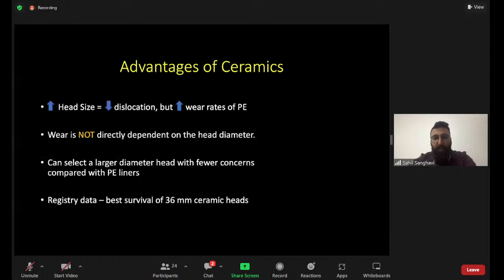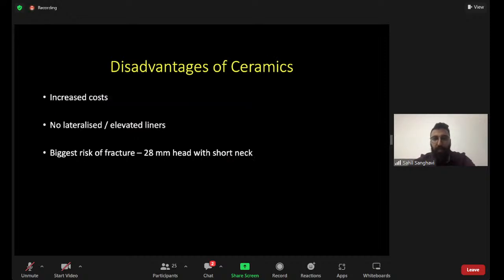The main advantages again of ceramic is that you can increase the head size, which was seen with polyethylene, where increasing head size was increasing the wear rate. But in the case of ceramic, wear is not directly proportionate to the diameter of the head. So you can select a large diameter head with fewer concerns. And again, registry data has shown that the best survival is with 36 millimeter ceramic heads.